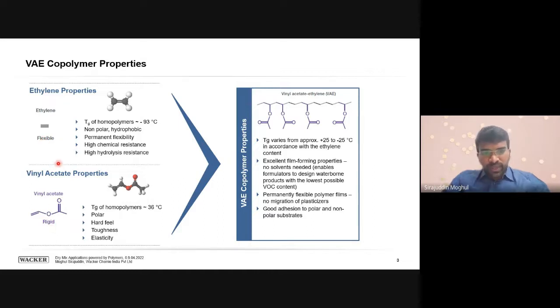So now you can play with the combination of these two monomers, which will help us to get whatever polymer we want. For example, if we want a hard polymer, we can increase the percentage of vinyl acetate in the formulation so that we get a hard polymer. And if we need a very flexible polymer, then we can increase the percentage of ethylene in the reaction so that we can get a flexible polymer.